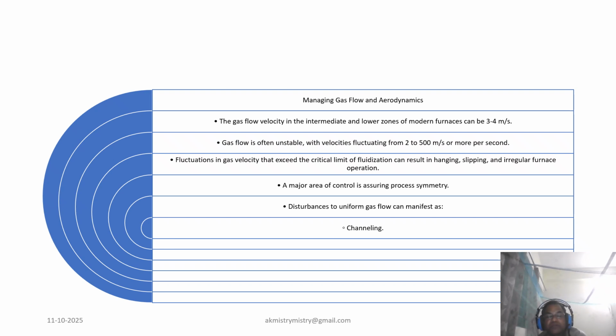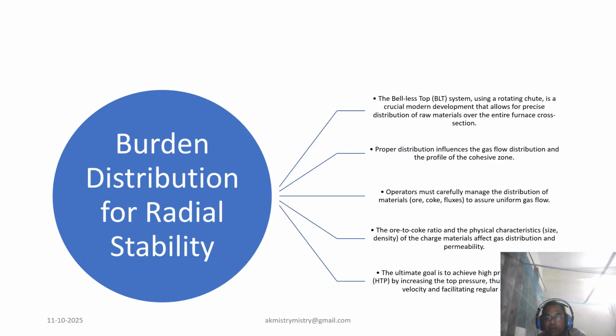The effectiveness of this management is judged using the permeability index, that is Q, which is a primary indicator of the furnace thermal state. The primary operational mechanism for managing gas distribution over the radius is a precise burden distribution. Modern furnaces rely on the bell-less top system, which offers the flexibility to lay down material anywhere in the stock line. Uniform distribution aims to create a uniform gas flow.